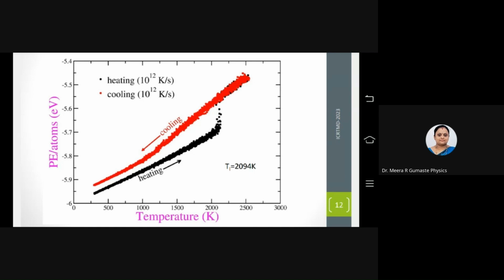The black curve represents the melting curve, that is the heating curve, and you can see it's monotonically increasing up to some 2100 Kelvin, and then there is a sudden jump, and after that it is again linearly increasing. That jump actually marks the melting of the crystal. So that represents the melting temperature or the liquidus temperature. The liquidus temperature here is 2094 Kelvin, and the red curve is representing the cooling curve. The TL is written here, that is the liquidus temperature, where the crystal melts and becomes liquid. So that is 2094 Kelvin for this aluminum zirconium alloy.